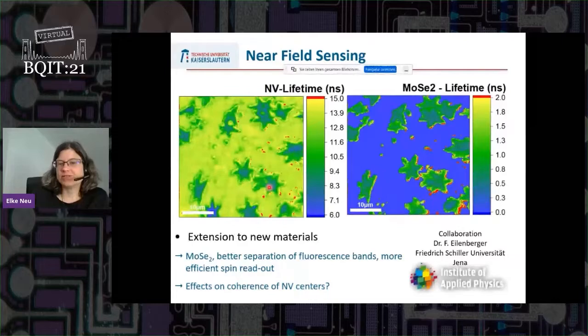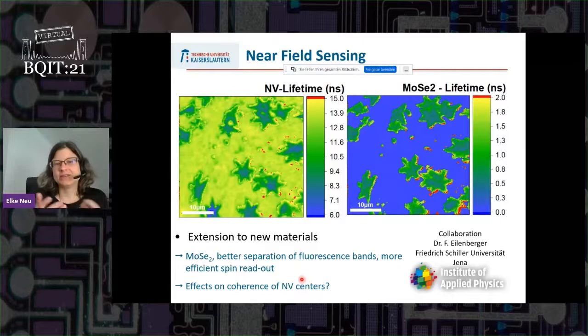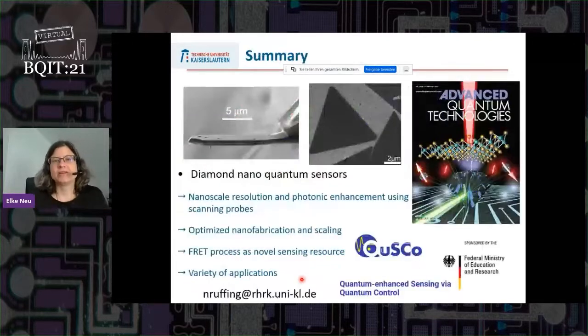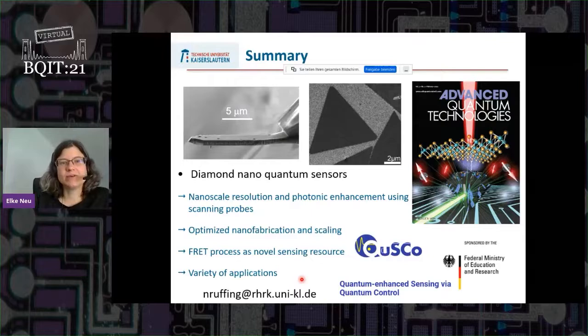And we can make more sophisticated spin measurements, and we are currently working on seeing the effects of this two-dimensional material on the coherence time of the NV spin, not just on the optical lifetime. And this is very interesting also to see if you can really combine this with the FRET and still see the coherence of the system.